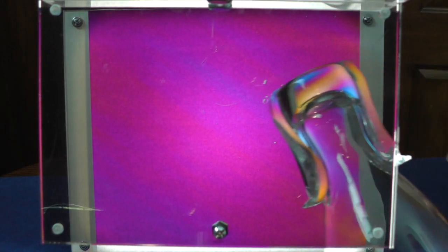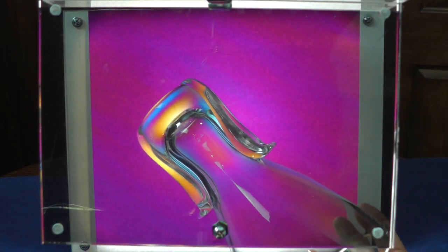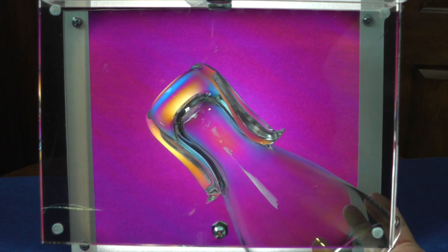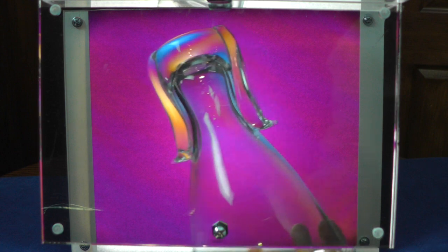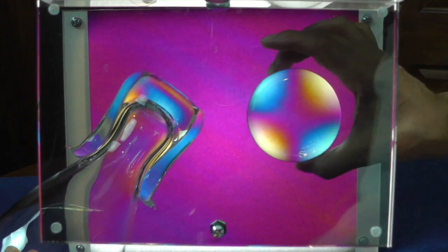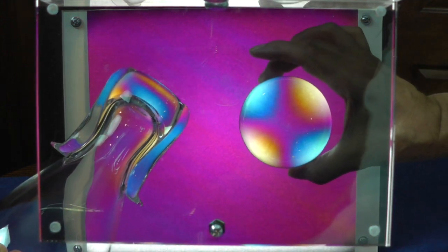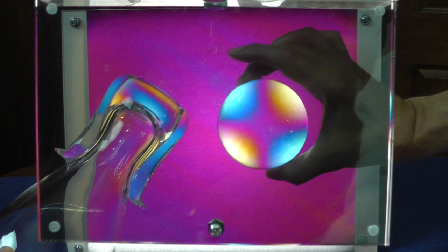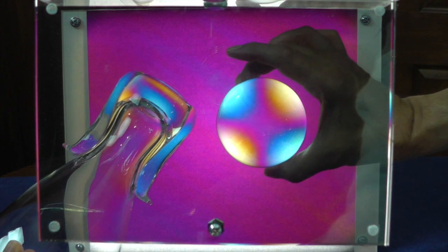You can see in this vase that there is a light strain in the glass. This is pretty typical of a vase that has a heavy section attached to a thinner section of glass. I used this gob to the side as kind of a benchmark. It's about 1 inch thick and about 3 inches in diameter.